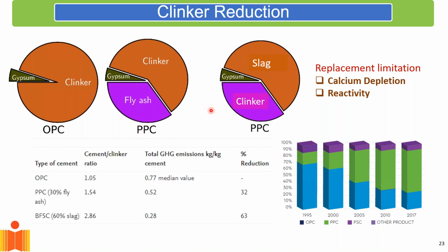Now, if you look at the blended cements, this is the story as it has evolved over the years. Today, more than 70% of the cement that we're making is in the blended form, whether it is PPC or PSC. The problem is that with slag, we don't have adequate slag. We don't have enough slag that we can start making more of PSC. Otherwise, we could really bring down the clinker factor in cements.